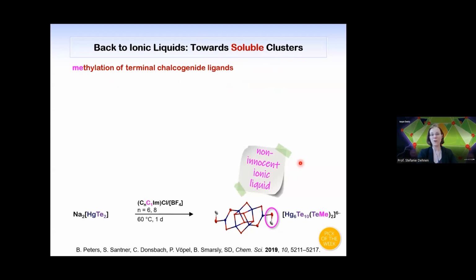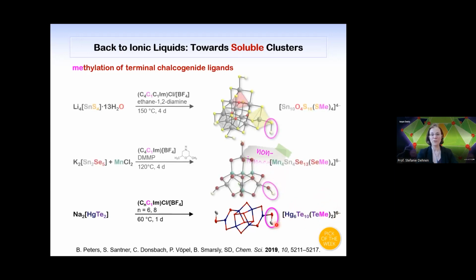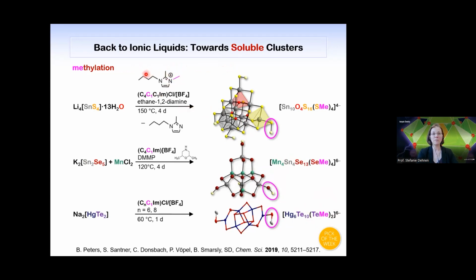But then we found out, and this was something that I mentioned only briefly, that ionic liquids can be non-innocent, producing methylated clusters. And we showed that this could also be done with selenide and sulfide clusters, not only with the telluride chemistry. And how that goes is shown here. So you take the imidazolium cation in your ionic liquid and you strip off one of the methyl groups that will just go to the terminal ligands and form the neutral imidazole, which we can show by NMR spectroscopy.